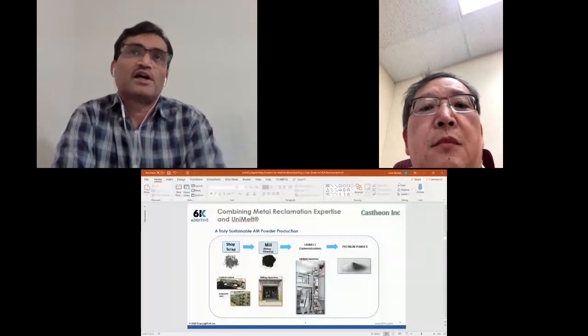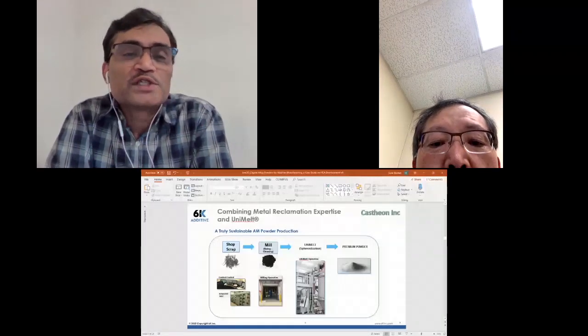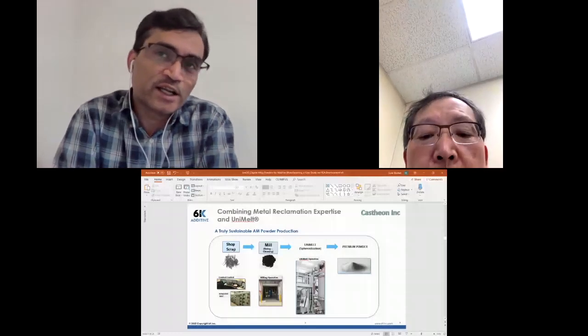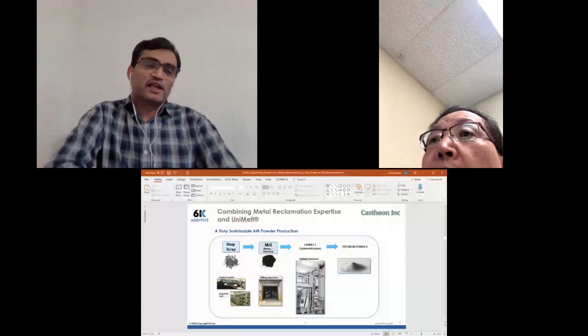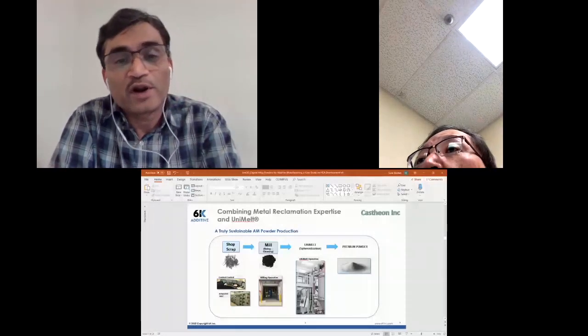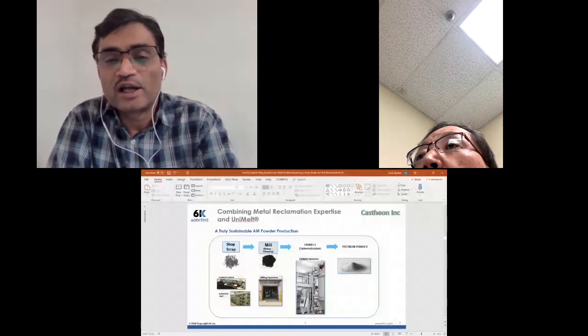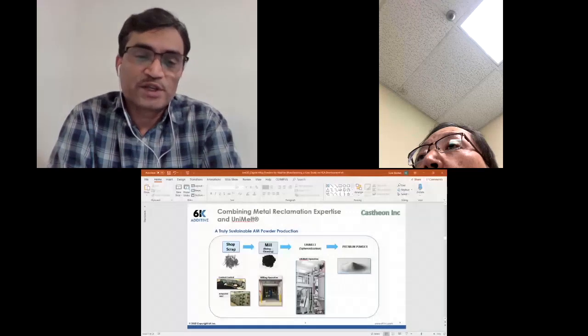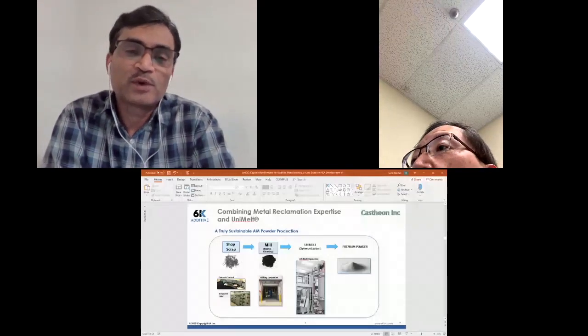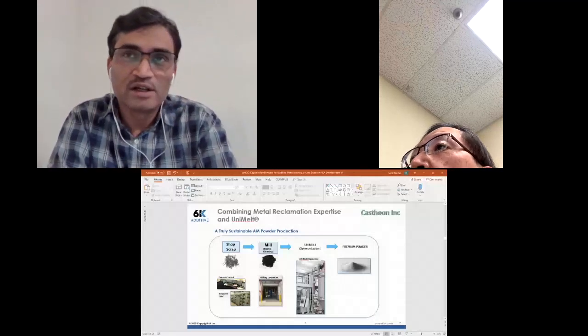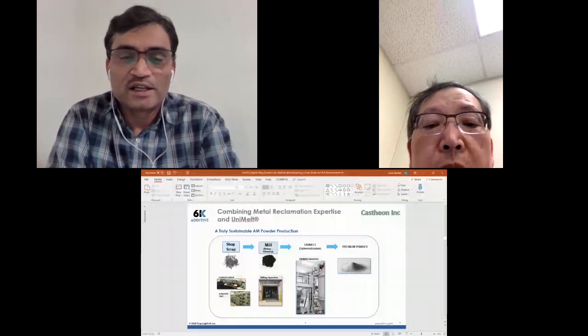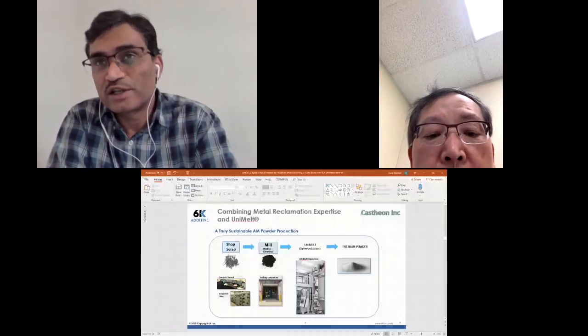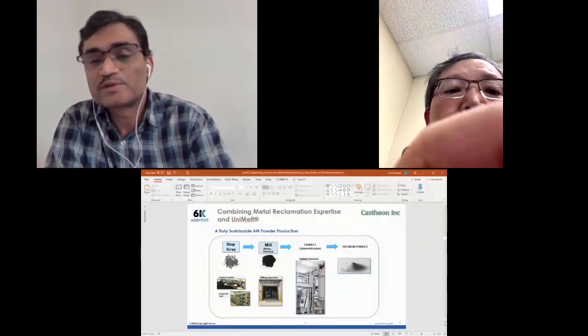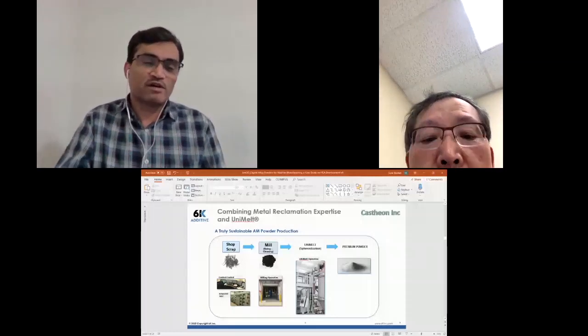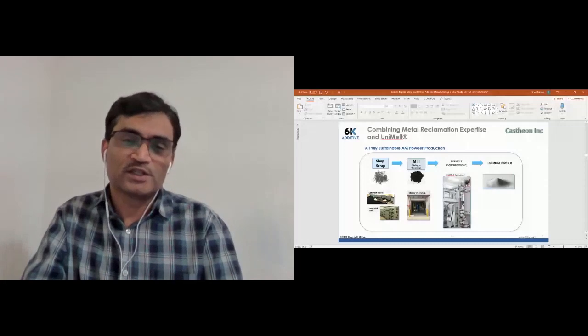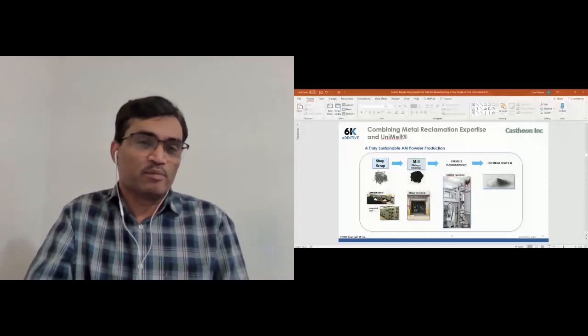And we also have another sister company just outside of Pittsburgh, which specializes in metal reclamation, especially titanium metal reclamation. Basically, they take the shop scrap and melt it down and produce a product which is used as an additive in aluminum melting companies for titanium addition. We can leverage their processing technologies from scrap to milling and controlling the particle size, and use that as a feedstock for our UniMelt spheroidizing system to produce spherical powders. So it's a great combination of their expertise and our expertise to produce premium powders in spherical form.